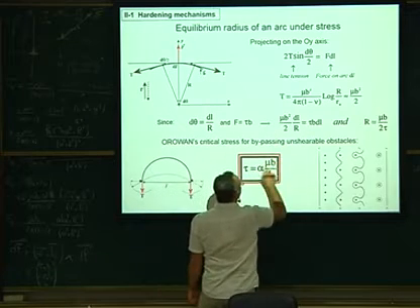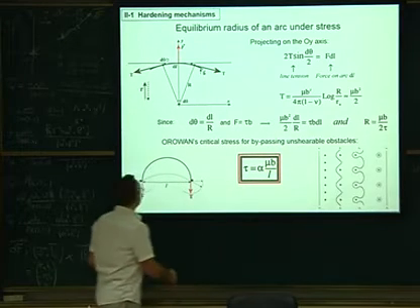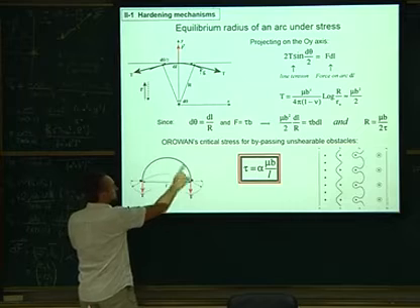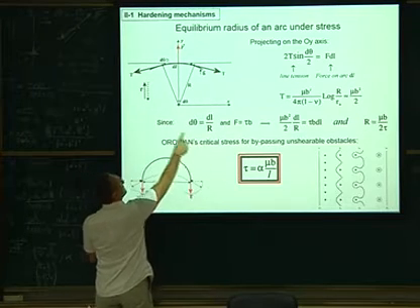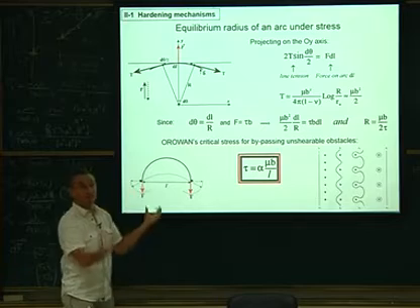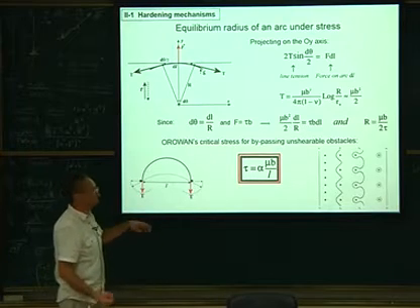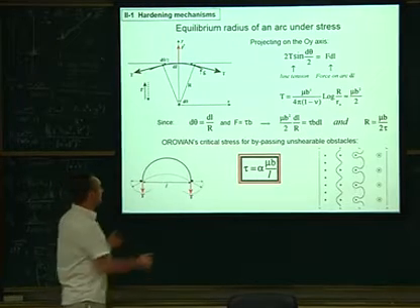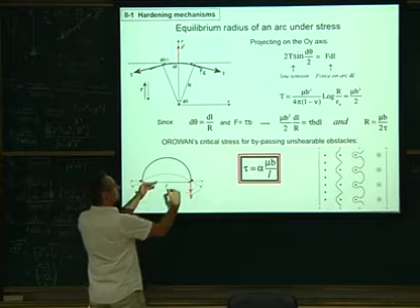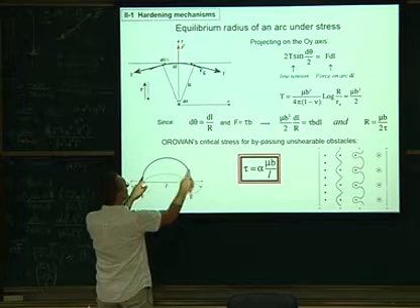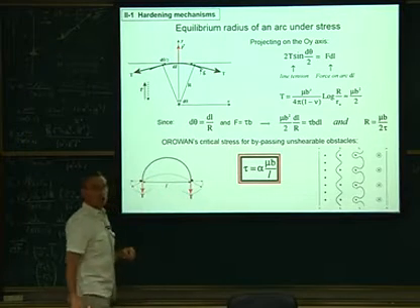Tau is equal to alpha mu b over r. I should write r also if you want. And when it is here, this radius is very small. When you increase more, your dislocation will be like this. The radius is again bigger, so the stress will be lower. The stress needed to move it will be lower. So first you start with a weak stress. It will increase to bow, and the critical stress will be when this shape is on your loop.